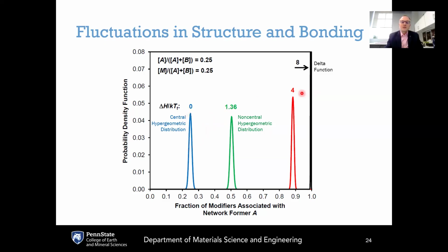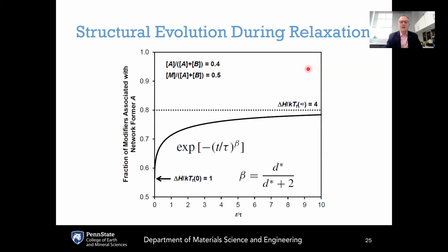And you can see these fluctuations evolving, where if you've got a system that's completely dominated by entropy, this distribution here is actually a central hypergeometric distribution, because the energetic differences are either non-existent or they don't matter. If you have a delta H over KTF that is not equal to zero, then that central hypergeometric distribution becomes a non-central hypergeometric distribution. And if you take the limit of a really large delta H over KTF, then that actually minimizes the fluctuations, as this non-central hypergeometric distribution collapses into a delta function in that limit.